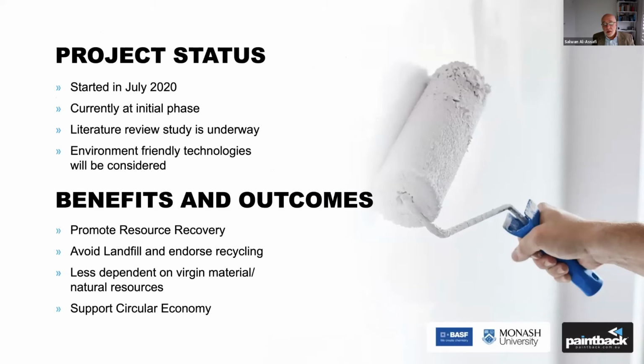So the water-based paint gets sonicated, and they study more than one process, but in general it gets sonicated and then separates the polymer from titanium dioxide, and then you end up with an emulsion which you can put back in the paint. So this is another circular economy solution. So you separate titanium dioxide from the rest of the paint, you remove it, and then you put it back in a new paint formulation that can go to another customer and they can use it as paint.